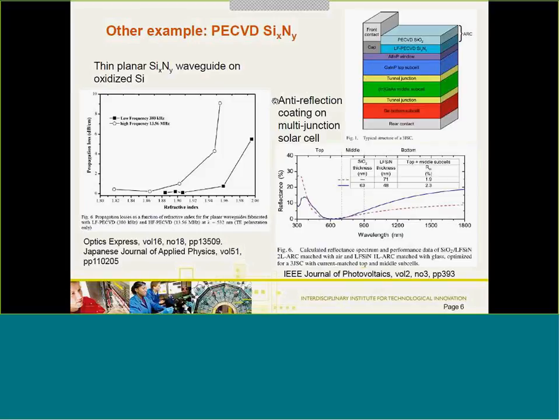Another example is PECVD nitride. We've made some thin planar silicon nitride on oxidized silicon. We've fine-tuned the recipe in order to change the index of refraction and the absorption coefficient of our nitride. Doing that, we managed to have some areas where our propagation losses were less than 1 dB per centimeter, which is actually a transparent material.